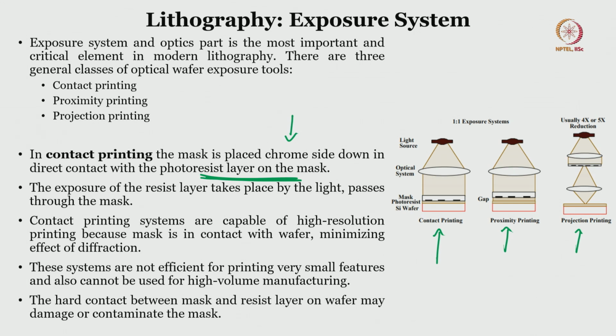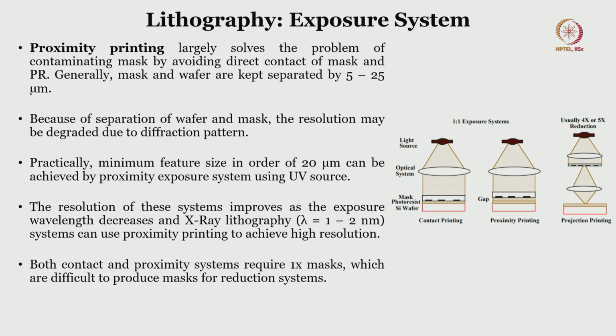Contact printing systems are capable of high resolution printing because the mask is in contact. So, the resolution is good, minimizing the effect of diffraction. These systems are not efficient for printing very small features and also cannot be used for high volume manufacturing. That is a difficulty with contact printing. Also, the hard contact between mask and resist layer on the wafer can damage or contaminate the mask. So, these are the limitations of contact based lithography, or contact printing.